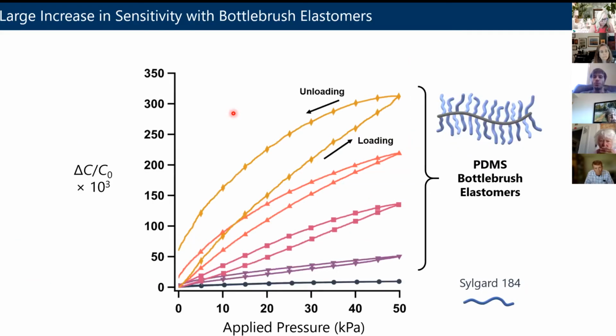Now, when you push on this device, you measure the change in capacitance, and the y-axis here is that change in capacitance normalized by the original capacitance, which we call C0. Just think about the y-axis as the signal you get out when you push on the device and you deform that soft elastomer in between the electrodes as a function, the x-axis, of applied pressure. And this is that low pressure regime we introduced early in the talk.